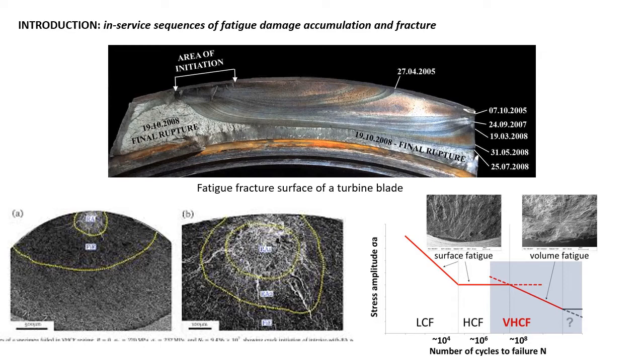The most demonstrative example of such behavior is the crack initiation in turbojet engine blades. At the initial stage, it can be provoked by high-frequency vibration leading to the very high cycle fatigue loading. Once the crack-like defect appears, the later stage of crack propagation is driven by the high cycle fatigue loading condition. Obviously, the kinetic parameters and therefore a corresponding fatigue life will be different for these stages.